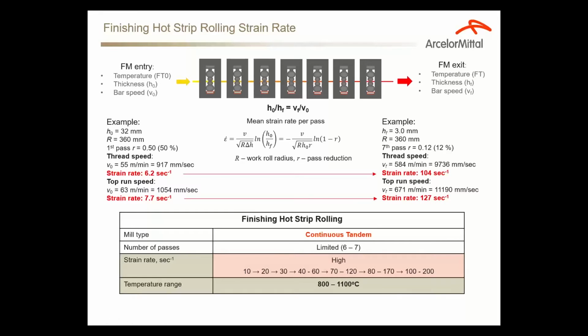Important is that the Gleeble machine cannot reliably reproduce very high strain rates, just because the time of deformation is very short. So we need to accelerate the ram and decelerate the ram in compression, for example. In torsion, it is easier to obtain this kind of strain rates, but the strain rate is not uniform if we're using the round bar sample. So this is a challenge not only for Gleeble machines, but for other machines to simulate more or less accurately the strain rates of about 100, and to make sure that the strain rate is uniform throughout the test. That is why we need some sort of translation algorithm to translate the results obtained at lower strain rates to what we can see in the mill.